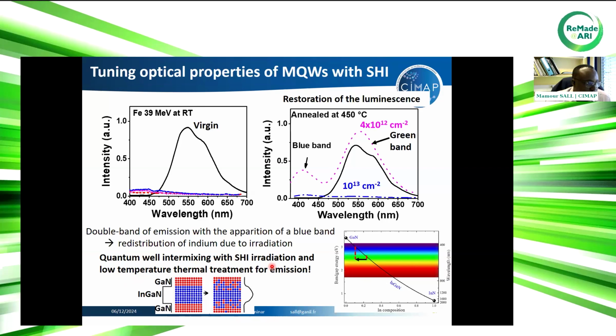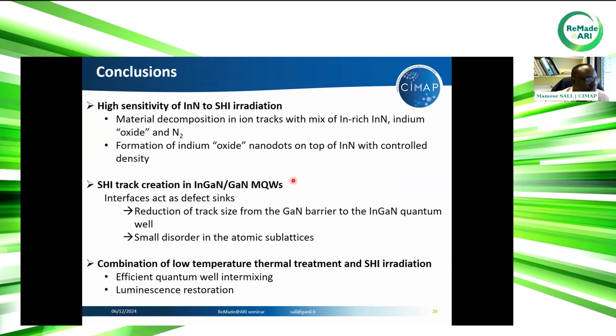This is a really great result, because we can keep the green luminescence. We can also see, by the appearance of this blue band, that we have created the quantum mixing that is needed for decreasing the polarization field that decreases the efficiency of emission of LEDs.